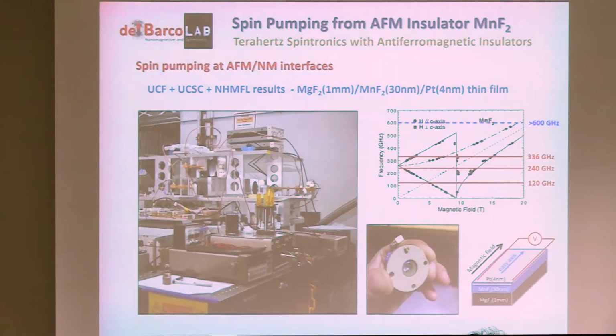high magnetic field laboratory in Tallahassee, and we used the heterodyne detection system where they can work with several frequencies, up to, I believe, 800 gigahertz, but the higher they go in frequency, the lower the power they get available. In the experiments that we tried, we just used these 3 frequencies, but still high frequencies, very monochromatic, not like in your case. They are able to select a very particular frequency, and then our sample looks like this, and it's embedded there. This is a quasi-optical setup, so the microwaves are conducted through air down to where the sample is placed, and this, of course, gets inside the magnet.